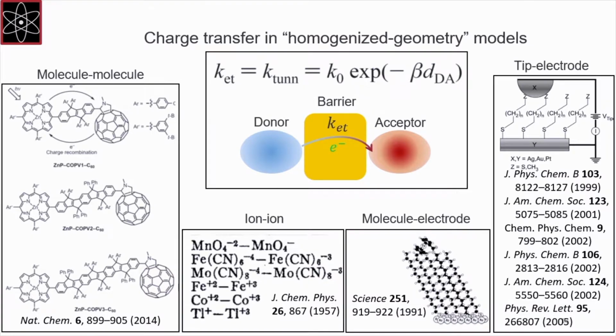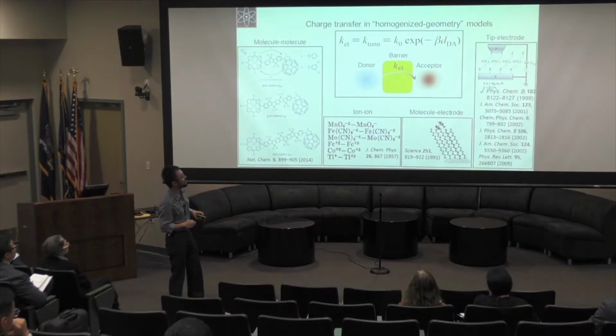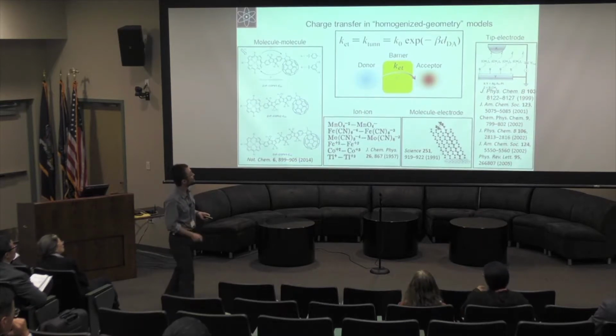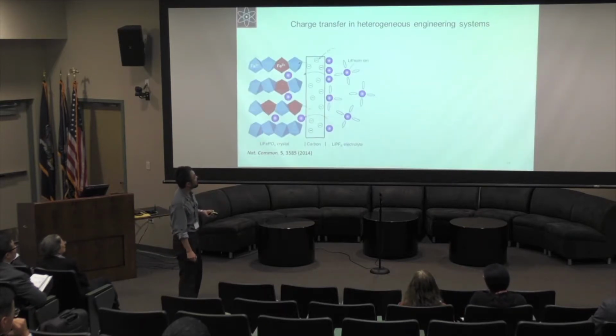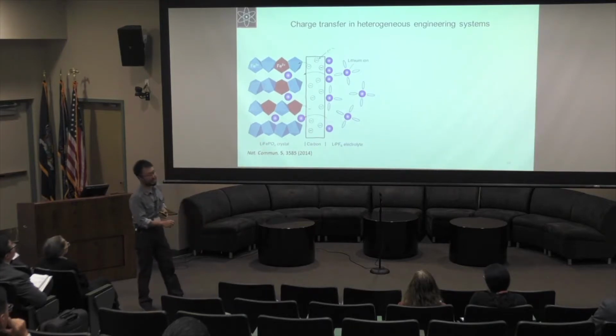And the conclusion from all of these studies that span more than half a century is that the first order reaction, the rate constant for that transfer process, k electron transfer, is pretty much a tunneling phenomenon, and that the rate decays exponentially with the distance between the donor and acceptor with some parameter beta. What about in the case of heterogeneous engineering systems? That's what people usually deal with in